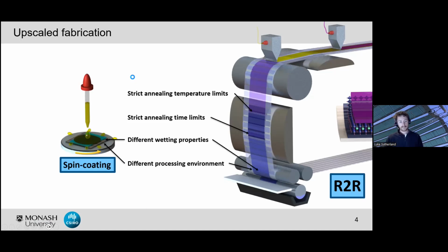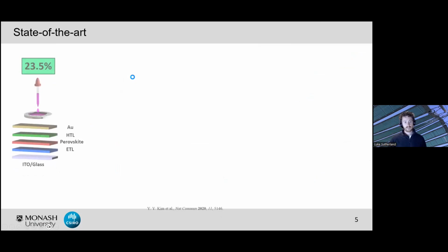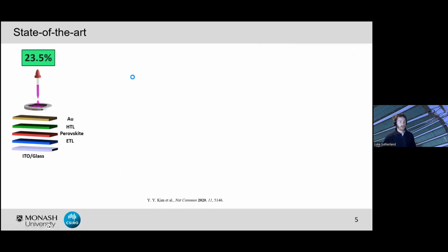Whereas for our glass-based substrates, we might be able to anneal our devices at 150 degrees for 10 minutes. It's a very standard operation. Whereas in our continuous roll-to-roll process, we're really limited to maybe 140 degrees, and we might have seconds, maybe minutes if you're going very slow. And so all of these challenges, again, another challenge there, different solvent drying kinetics, they accumulate. And within the literature, we see a vast difference between the efficiency for these spin-coated devices compared to the roll-to-roll counterparts. And so I'll just bring up one example here just so we can visualize what's actually going on.